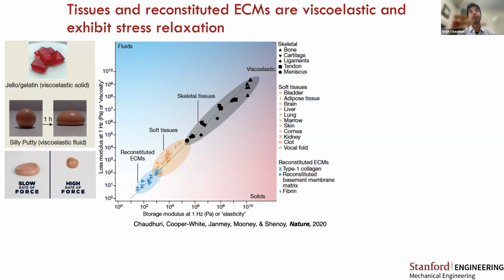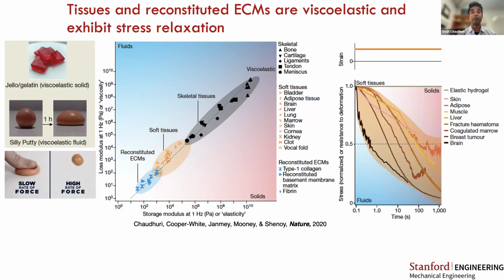And for all of these materials, we see that the loss modulus at 1 Hertz is about 10% of the storage modulus at 1 Hertz as well. So all of these materials exhibit a substantial viscoelastic quality or response, or they're all viscoelastic. So these measurements are all done at 1 Hertz. And you see a similar loss tangent, or ratio of the loss modulus to the storage modulus. But at longer times, you see some variation in the viscoelastic responses of these different tissues.